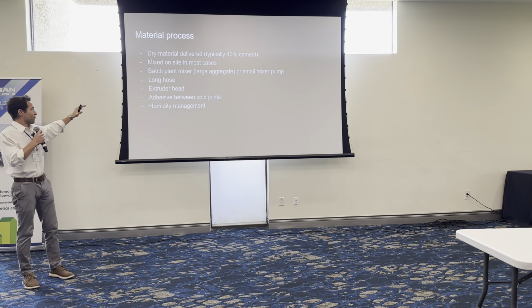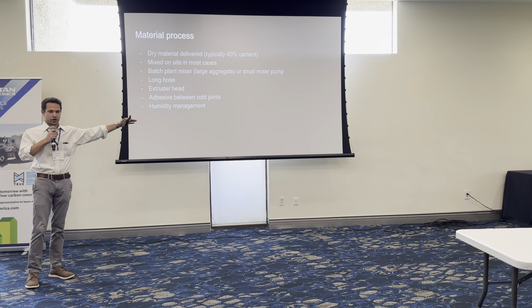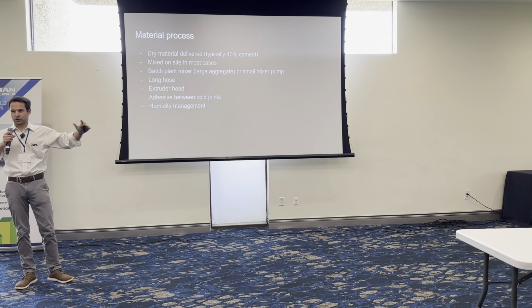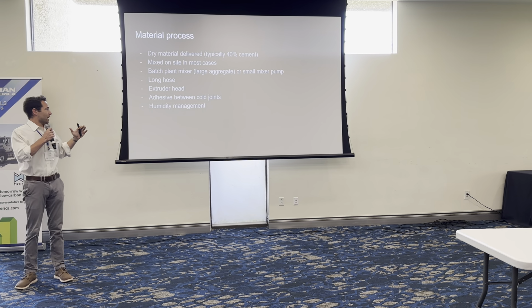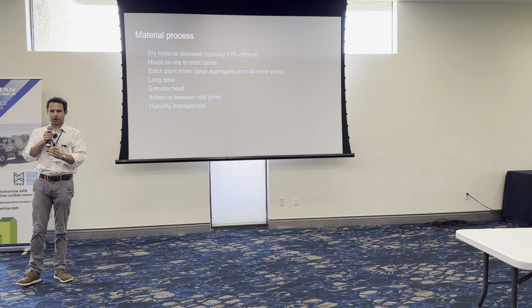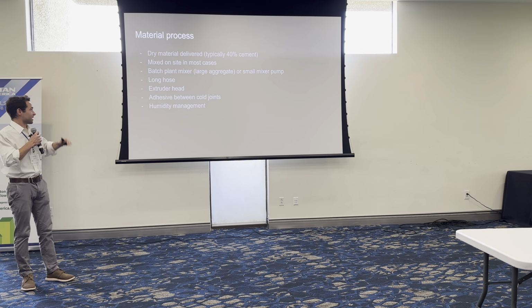From the mixer pump or batch plant mixer, it goes through a very long hose. It could be 90 yards for some of the larger gantry systems. And the hose is only 2 or 3 inches in diameter, so that pump needs to have a lot of power to push through the friction, especially at higher printing heights. A clogged hose is no fun.